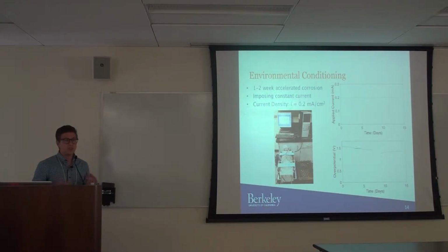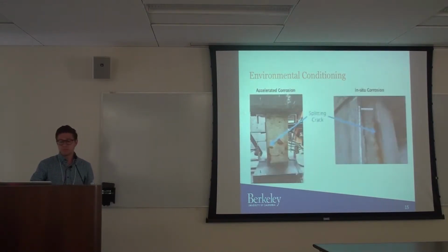And we see within 1 to 2 weeks cracks forming that are very similar to what you would see in a naturally damaged column. And we're going until we see cracks that are objectively similar in nature. So what we're looking specifically at is these long splitting cracks that form along the rebar. It's kind of difficult to see in this image on the left of our actual specimen, but there are quite a few cracks there that go along the rebar and a few transverse cracks. So we're looking at similar damage.